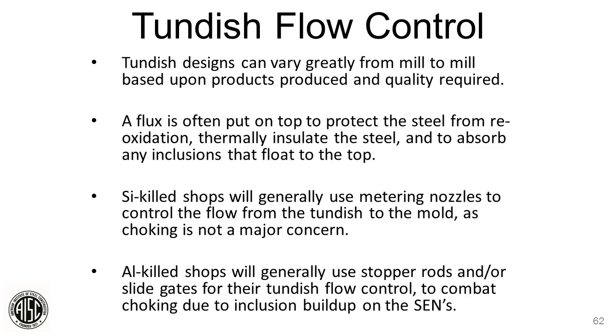So, like I said, it depends on what kind of shop you're in, what your Tundish design looks like. A flux is added to the top, again, to seal it off from outside air. Silicon-killed shops will generally use metering nozzles to control the Tundish to mold flow. And aluminum-killed shops will use stopper rods or slide gates. Basically, aluminum is very sensitive to oxygen. You've got to have that really, really sealed up well, or you're going to have big problems trying to cast it. So they have more sophisticated flow control devices just to keep the outside air from getting to the steel. Next slide, please.